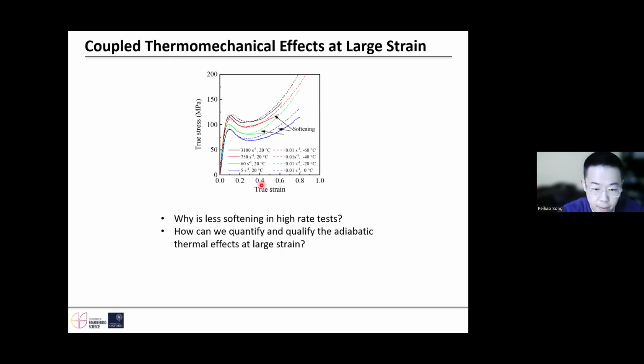Here, if we compare the rate-dependent test with the temperature-dependent test, from strain rate at 560 and 700, we compared with the low temperature test with the same or similar yield stress, we will see very evident thermal softening at large strain. However, for the higher strain rate test, 3000, compared with -60 Celsius, we didn't see evident thermal softening.